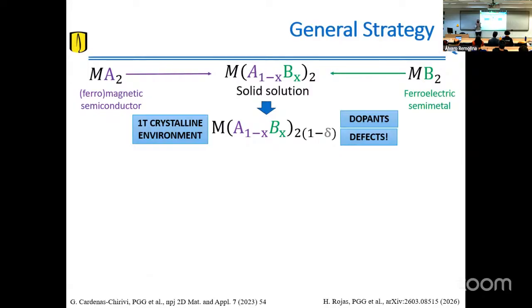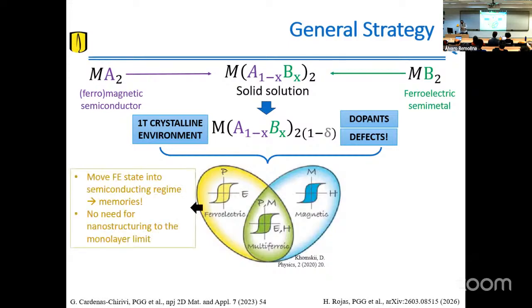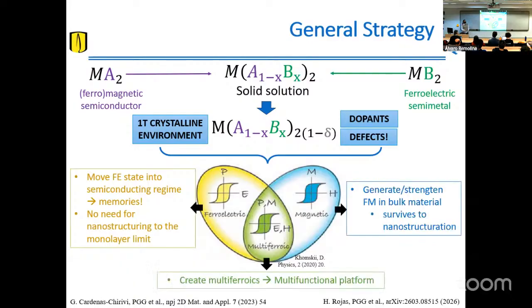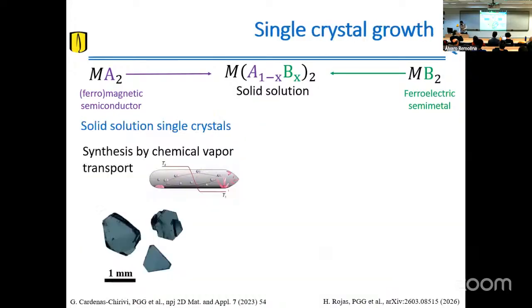It promotes locally, and it has been reported to promote, a 1T local structure around defects. It promotes the formation of defects because of natural processes in the chemistry of the growth of the crystals that we have in the lab, and it has dopants as well by substitution of these atoms. So by combining these compounds, we have not only strengthened the ferroelectric and ferromagnetic states in these materials, but we have also created multiferroicity in this family of compounds. And so far, we have the first report of multiferroicity at room temperature for this family of materials.